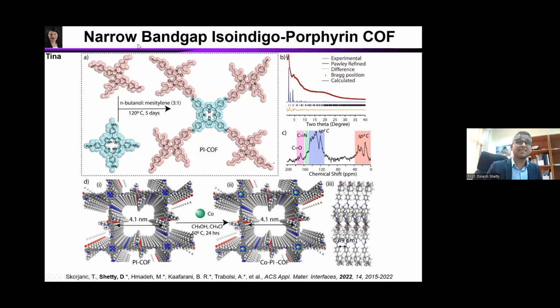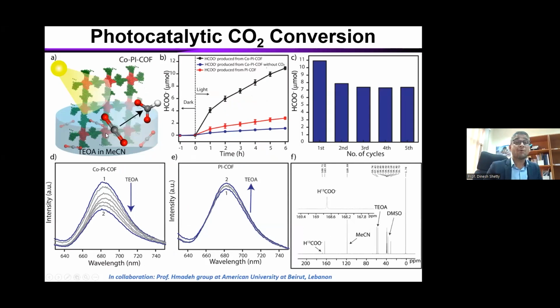And the good thing about this, it has a really narrow band gap, 0.7 electron volt. Okay. So then after that, because porphyrin is well known to hold a metal center, we did post-synthetic metallation, and we introduced cobalt because cobalt is a well-known metal center used for photocatalysis, and we did further characterization. And then what did we do with this? We used this for photocatalytic CO2 conversion in collaboration with Professor Hmadeh's group in Lebanon.